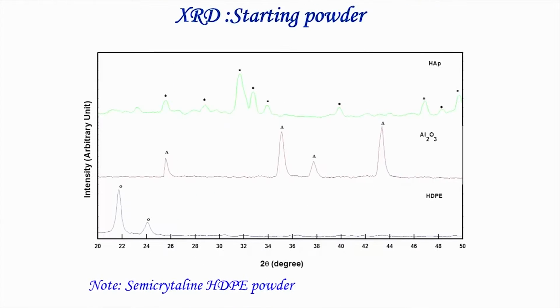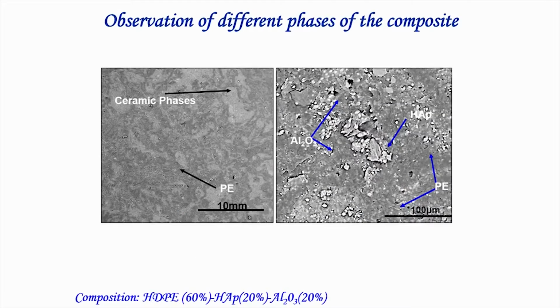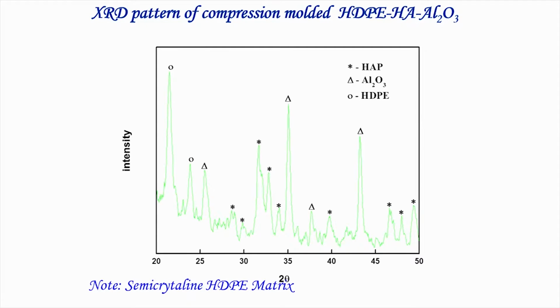Okay. This is the starting powder. For high density polyethylene, as you see, this peak is a little broad, so it is a semi crystalline polymer, not fully crystalline like many other polymers. Alumina also has crystalline peaks, and hydroxyapatite has very characteristic three peaks placed around 30 degrees of 2 theta. When you add these two phases, 20% hydroxyapatite and 20% alumina, you get a very clear semi crystalline peak, but this peak width is a little bit decreased in the compression molded samples, and you have the hydroxyapatite and alumina phases as well in the matrix.